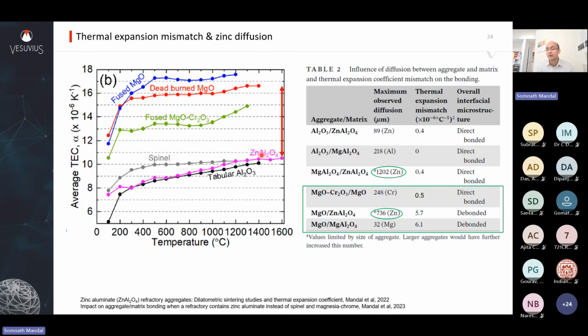If you want to make a really chrome-free product, you sell it not where you are trying to get low-cost material, but where chrome is banned. You have no option. That's where you do it. You see cement plants in Japan. They use magnesia spinel bricks in rotary kilns in Japan, because chrome is banned, since the cement has high calcium that forms hexavalent chromium through reaction with your chrome bricks. However, in India and a lot of countries, we have chrome bricks in cement plants. Why is that the case? Because there is nobody banning it.